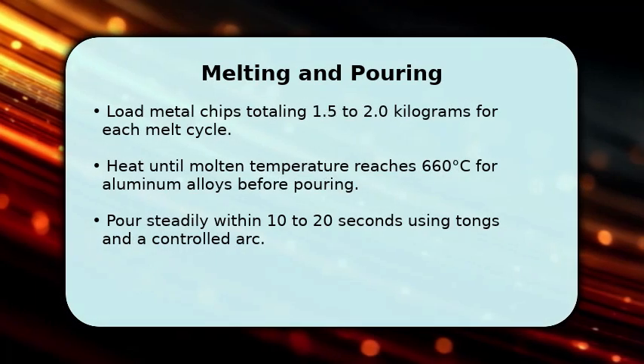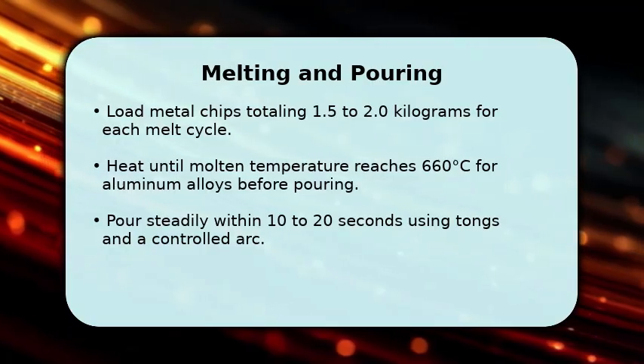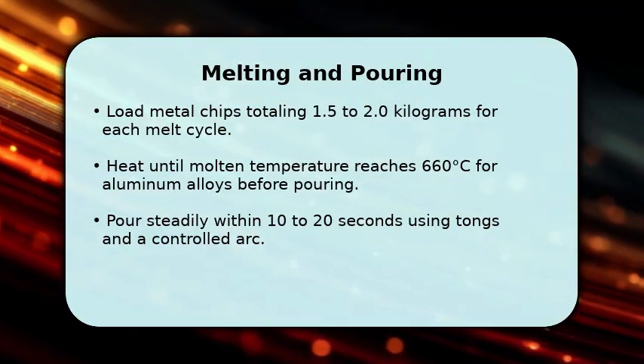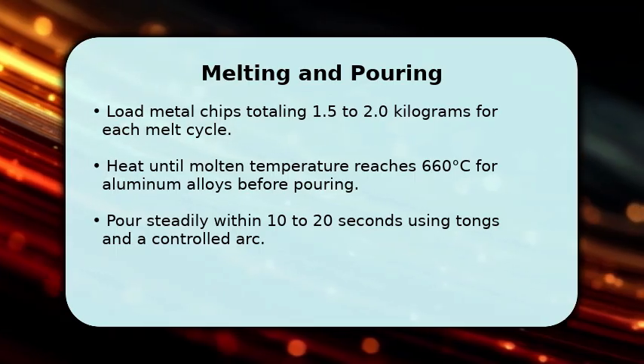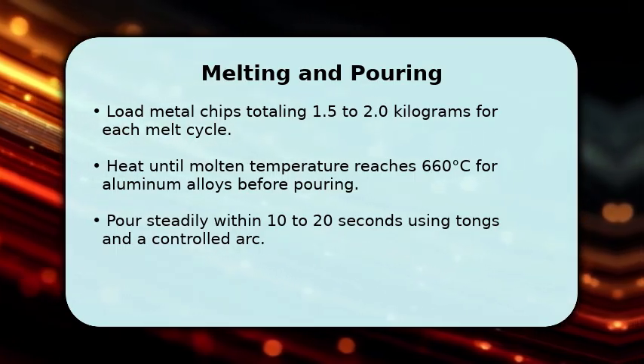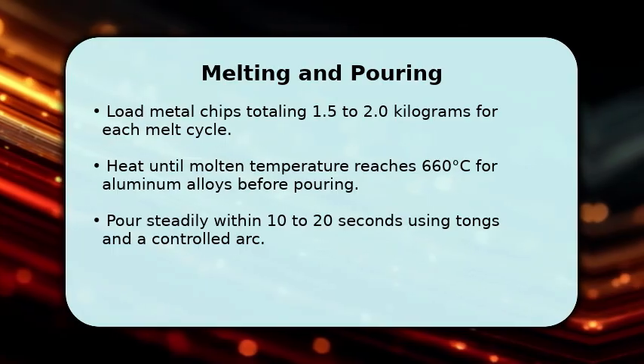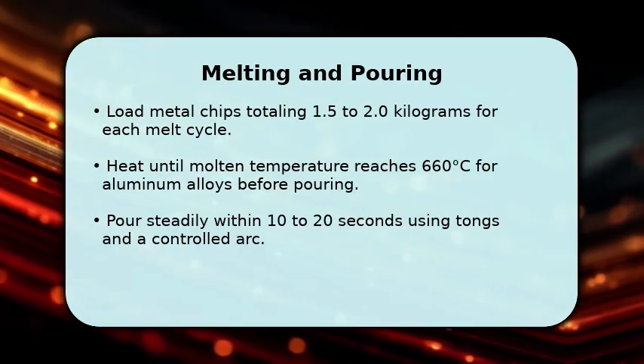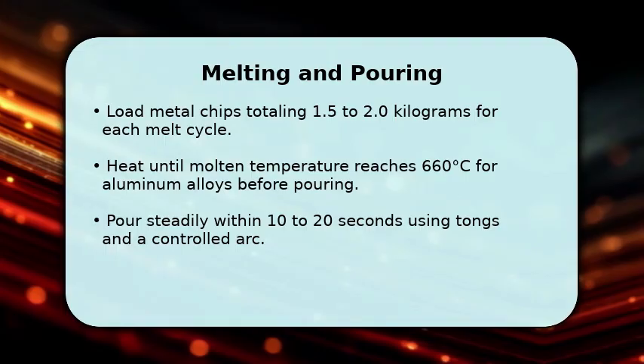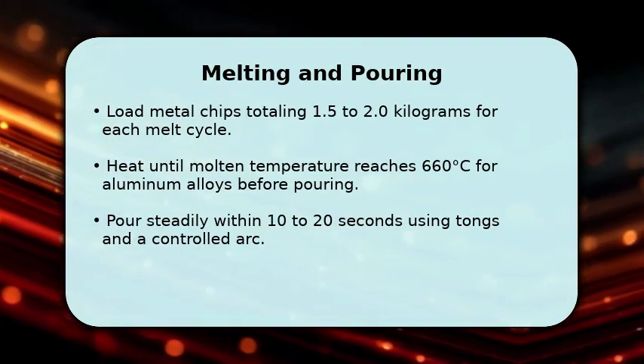Load metal chips totaling 1.5 to 2.0 kilograms for each melt cycle into the crucible. Start heating using the specified power setting and monitor rise with a digital thermometer. Heat until molten temperature reaches 660 degrees C for aluminum alloys before preparing to pour.